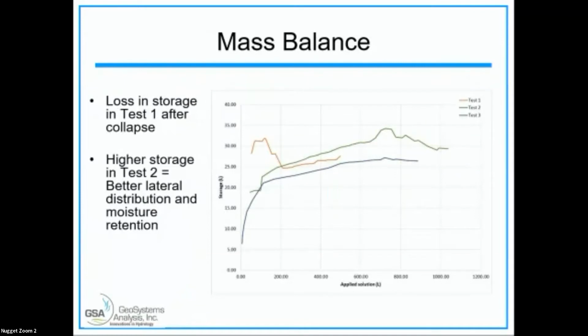So what does this mean? We know from the ERT analysis as well as the neutron probe analysis that there's quite a bit of variability in the outside part of the column. And what was also interesting was that in the fast ramp up, we could see it was very distinct. And I didn't put this in this presentation just for the sake of time, but with the neutron probe data, you could see that it was dry at the surface and very dry at the bottom. And then there was this bulge in the middle of moisture content.